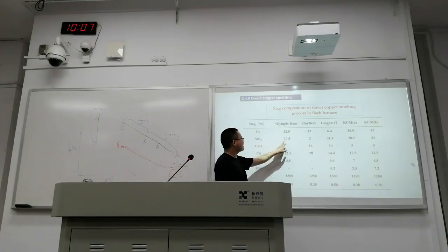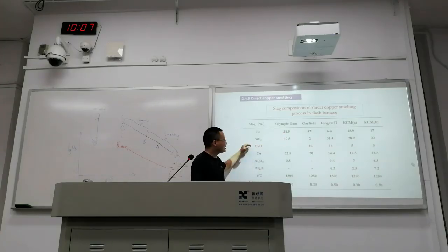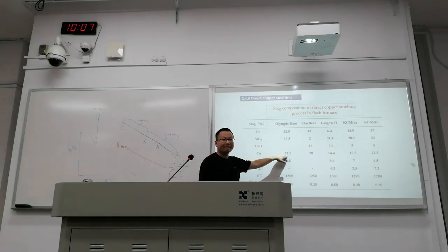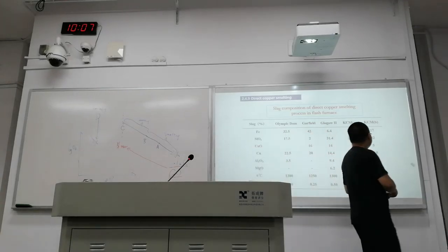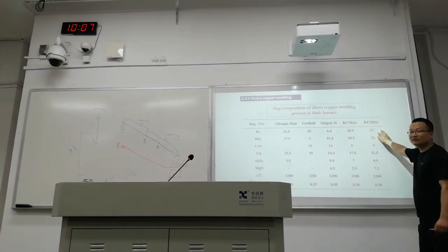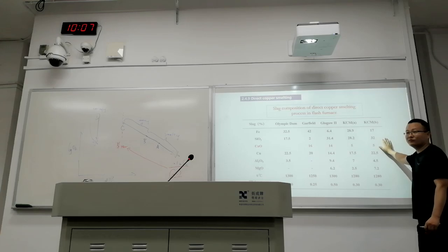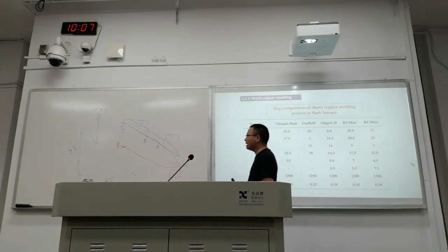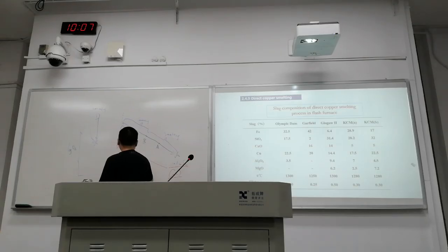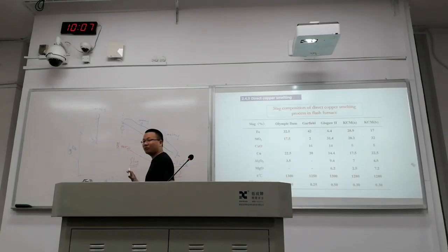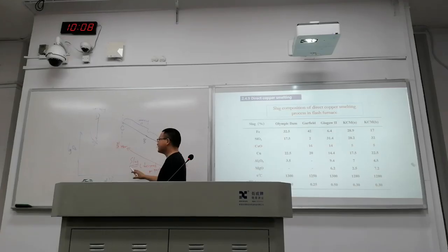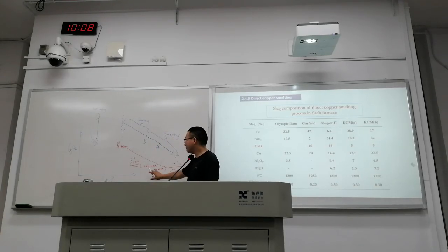So only that, the slag you are checking. So iron, silicon, without calcium oxide, and a big amount of copper. And if we are checking the other factories, smelters, they have iron, they have silicon, they have calcium. So 3 of them. So when we are having this one, actually I would like to see slag is not uniform. So it should be designed individually or on purpose.